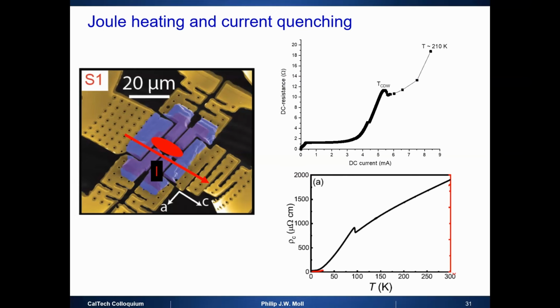As you increase current, joule heating, I squared, will give you temperature. So the thing starts to slowly warm up, and then as you yank through more current, it heats faster and faster. And so what is important now is that here there is a bloop where it goes back down. So putting more current in gives you a little bit less resistance. Then if you look at the resistance without all of this current bias as a function of temperature, you see that the charge density wave transition comes in as this little nose here, right? And so that's what happens here. So this is the current driven demise of the charge density wave transition. And then you can heat more and more, and you end up at something like 200 Kelvin, while the system still stays at its 2 Kelvin bath, right?